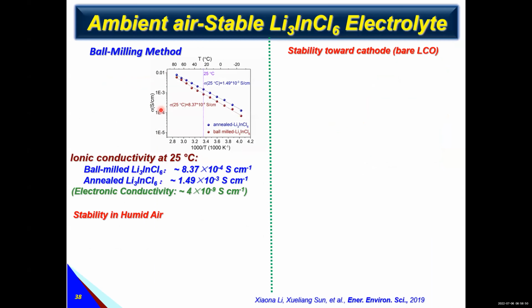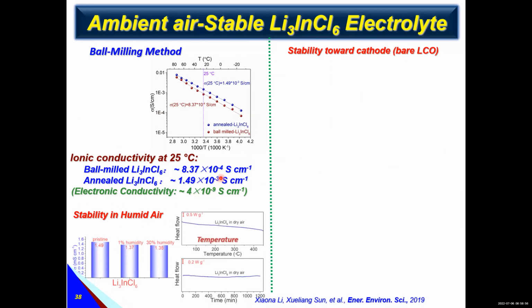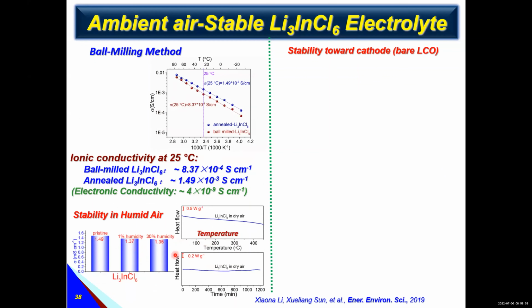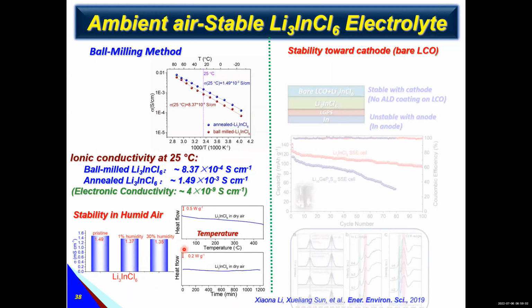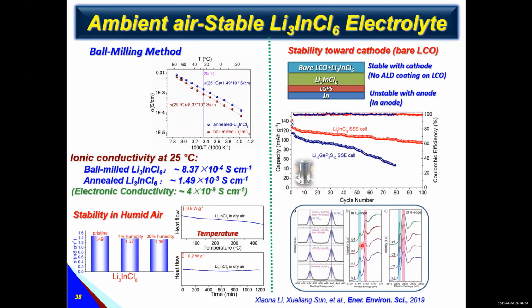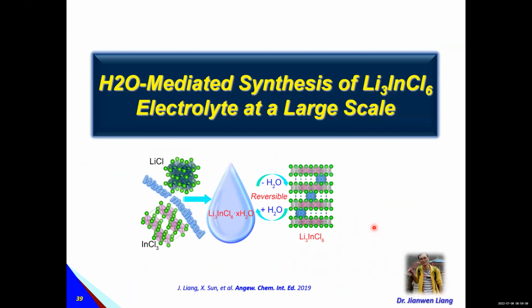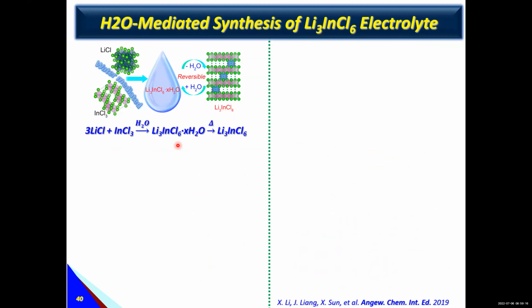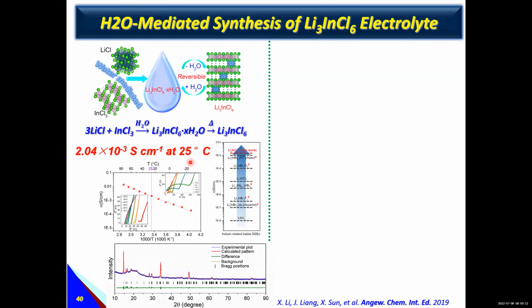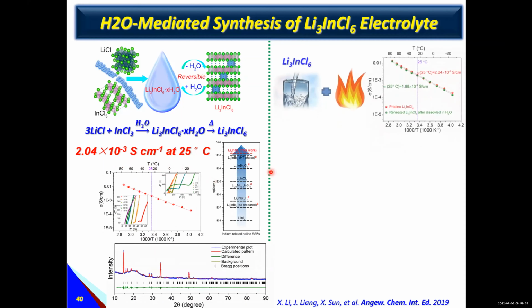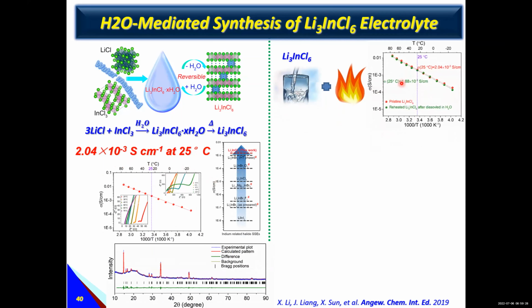Just using ball milling, we found a simple process that gets 10 to -3 ionic conductivity. Also, air stability is very good. We demonstrate the battery is working and also stable with the cathode without coating. After this ball milling method, we also tried to achieve mass production. We developed a liquid solution method. We just use a very simple process to put things together. After annealing, we get very high ionic conductivity at room temperature. Interestingly, we put it back in water after heating, and it maintains the same ionic conductivity.